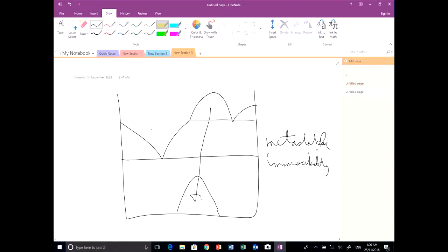Now this is cheating a little bit because it's not at equilibrium, it's metastable. So what happens is that two-liquid immiscibility gap is retained upon cooling. So we've frozen in the liquid microstructure, and we end up with a phase assemblage of frozen amorphous liquids. Although it should be crystalline, it should be A and B, but it's not. It's frozen in two liquids. So that's a metastable miscibility gap. Okay, so sometimes you see that, and you'll pick that because there's a miscibility gap and then a matching one down underneath.